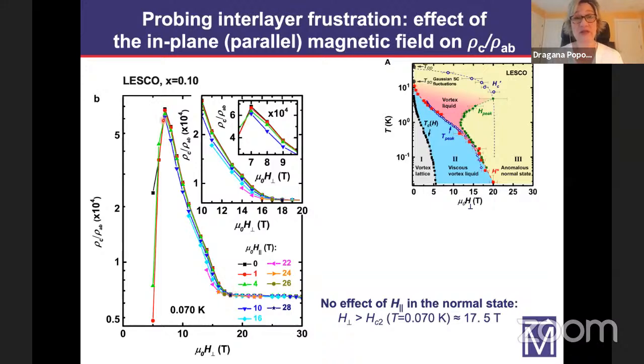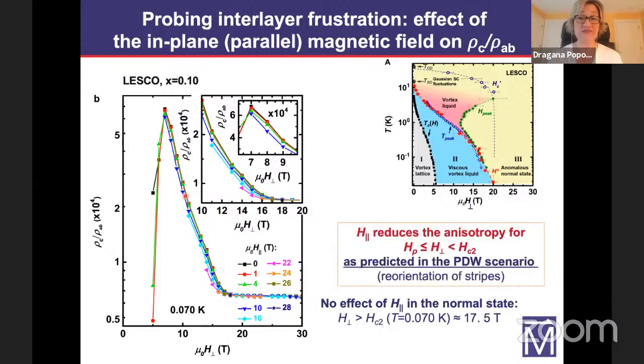However, between the layer decoupling field and the upper critical field, we see that the anisotropy ratio decreases exactly as predicted in the pair density wave scenario. This is maybe not so easy to see on this main plot because this is a log scale, and this is why we have this inset, which is a blow up of this region close to the upper critical field. And the smaller inset is a blow up of this region near the peak, near the decoupling field.